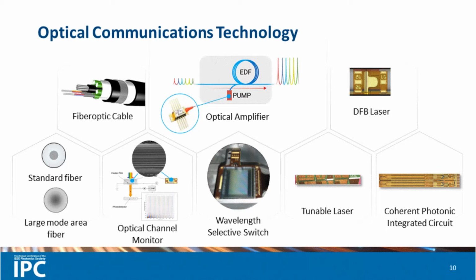The most prevalent technology for this optical channel monitoring today is based on a thermally tunable multi-layer stack of amorphous silicon and silicon nitride that lets specific wavelengths reach a detector based on the tuning of the stack temperature. Wavelength selective switches were also developed, employing liquid crystals to switch and attenuate wavelengths and to optically route individual channels to different fibers by leveraging diffraction and polarization.